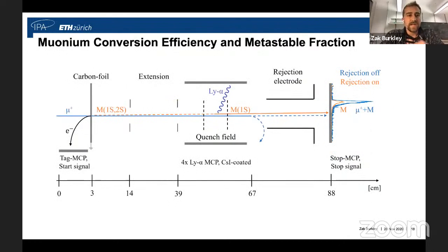And last year, we had a couple-day beam time at PSI to test our detectors and our tagging method. What we did is we had the carbon foil, our tagging MCP, that when the muons knocked off these secondary electrons. And then we have our quenching field and our Lyman alpha detectors. And then we have a rejection electrode at the end. So when the electrode's on, only muonium makes it to our back detector. When it's off, muons and muonium.